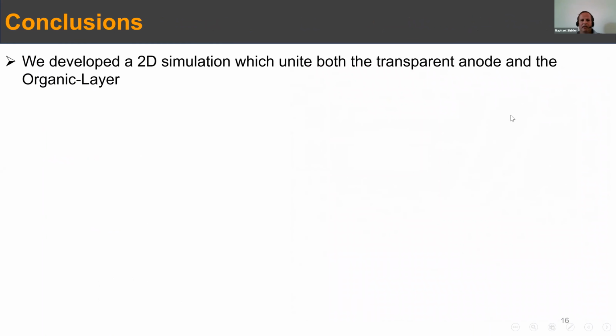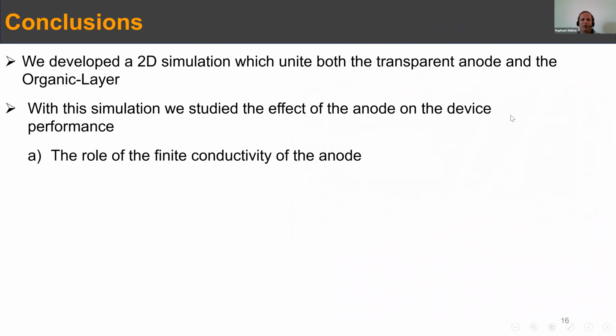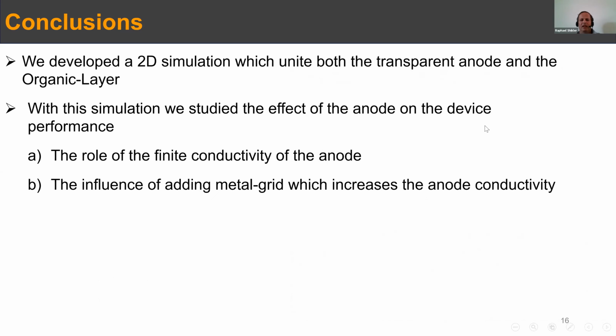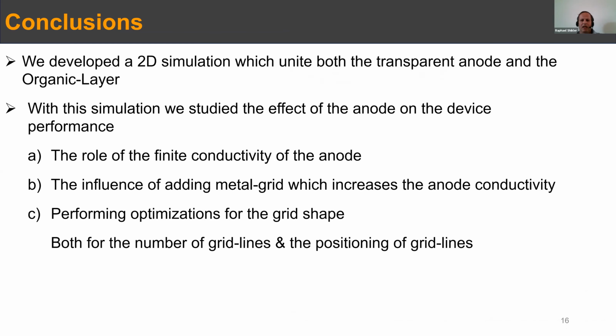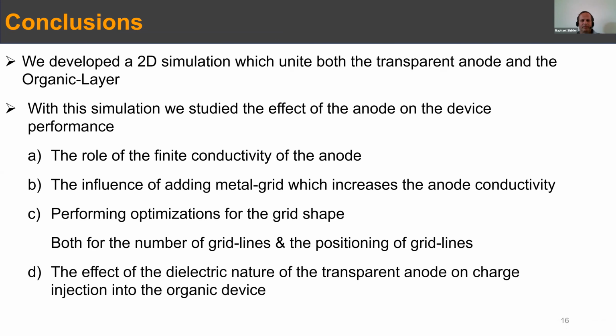And I think that this is summarized here: when we develop a 2D simulation which unites both transparent anode and organic layer, we can study the effect, the role of the finite conductivity. We also modify then the boundary condition for the charges due to the changes in the potential, which is also attributed to that, and you can see how this works. And we also did some optimization for grid shape and positioning. Thank you.